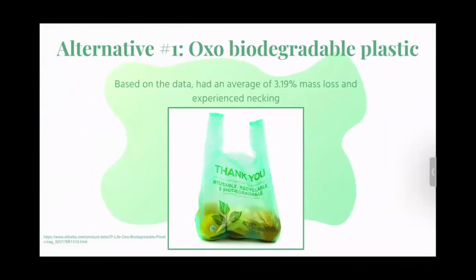Based on my research analyzing biodegradability tests and tensile strength tests, I found that an oxo biodegradable plastic would be the best choice for a polyethylene alternative in the dental industry. The oxo biodegradable plastic had an average of 3.19% mass loss over the time period, a higher biodegradability rate than the petroleum-based plastic that had an average of 0.014% mass loss. Biodegradability tests simulate the plastic after their single use in a real-world environment, a time that is currently being overlooked in the making of these material barriers.